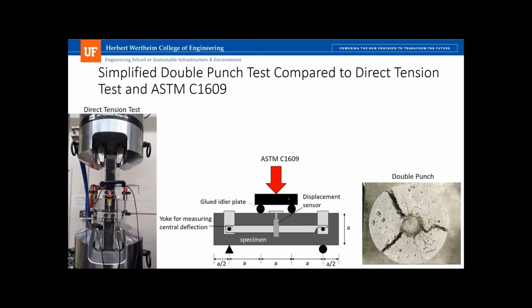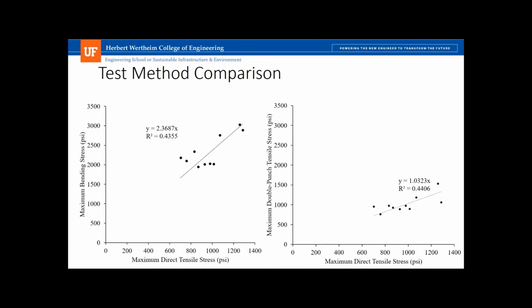Okay, so if we compare the results of our double punch test compared to our direct tension results and our flexural test to see how it performs, we find that we get very nice correlations between the direct tensile strength in double punch and our direct tensile results. We get the same with our direct tension versus our flexural. You get nice correlations no matter which test method you use. You just have to be careful that with the flexural test, you're really getting a modulus of rupture, not a true tensile strength, just using that simple equation.